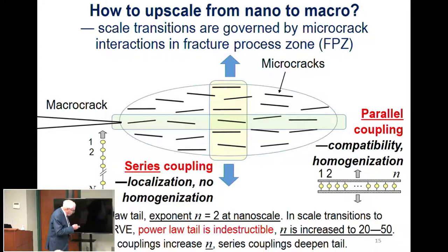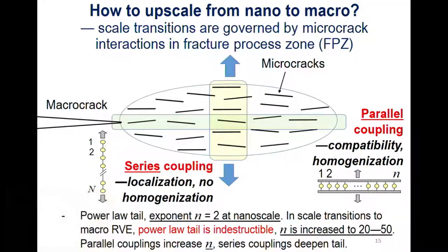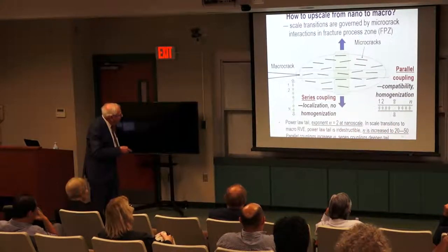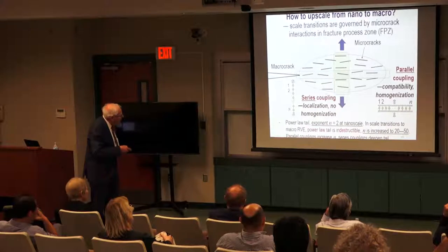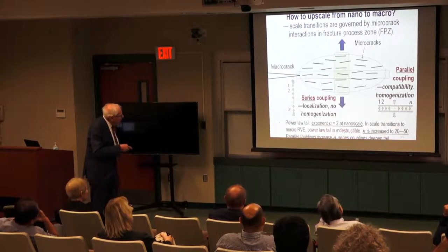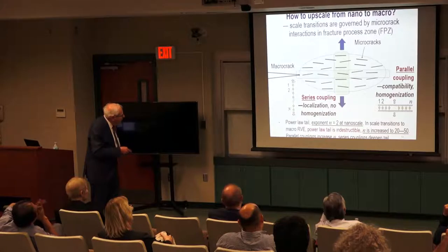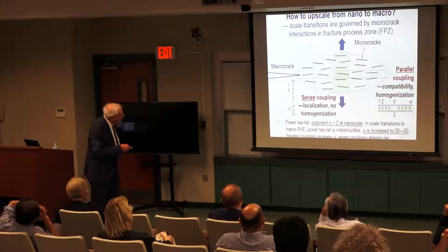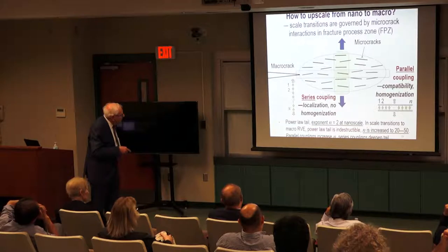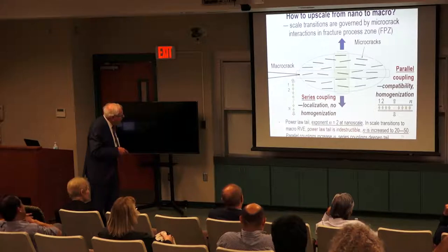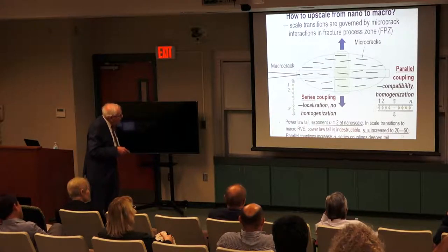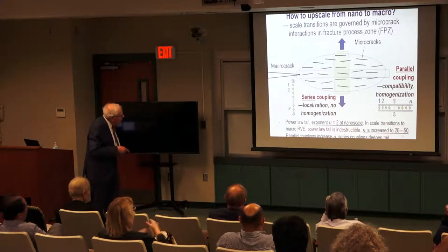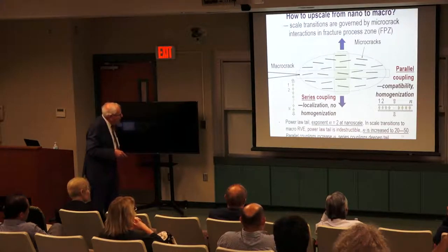And the failure or propagation then requires what? You can imagine a process zone where there is already a formed open microcrack. Microcracks are obviously mostly aligned in mode 1 loading and they have a tendency to localize, so that acts like a chain, if they always localize to failure at one point. And there are some other microcracks which are constrained laterally by compatibility condition, and that behaves like a fiber bundle.